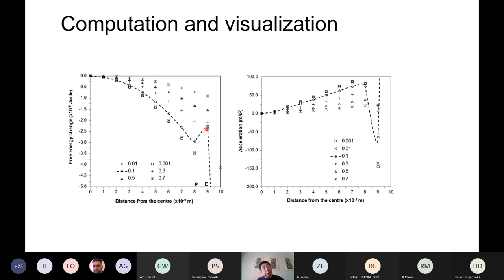And then once they approach the surface, the electric current tries to push the inclusion away, so therefore the free energy reduces drastically. So mainly, this part is the most important. You see, different points actually represent different electric conductivity ratios. This one has a ratio of 0.7, which means the electrical conductivity of the inclusion is about 70% of liquid steel. This one is a lot smaller. Its conductivity is about 1% of the electrical conductivity of liquid steel.